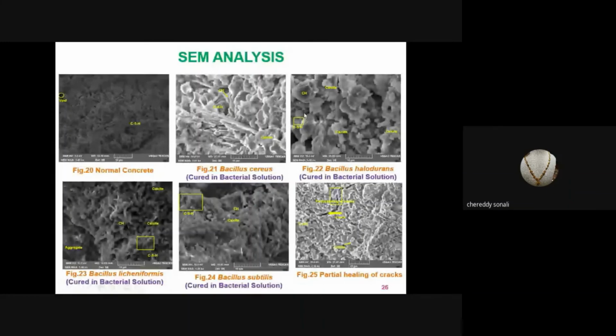In the normal concrete SEM image, you can observe the void space, but in the next 4 images that were sprayed with bacterial solution, no void space was found. We can clearly see the calcite and CSH gel formation in all these 4 images. And in the last image, we can clearly see the partial healing of cracks, which was found in the same image.